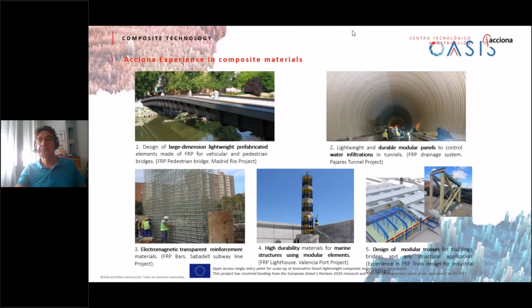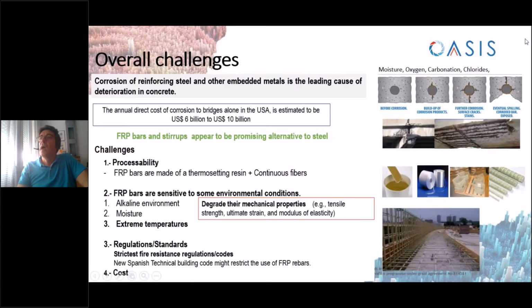So now, the question is, what are the challenges that Acciona proposed to OASIS? We are aware that in most civil engineering structures, corrosion is the main enemy and the leading cause of premature failure. The annual direct cost of corrosion in the US is estimated between 6 and 10 billion US dollars. In principle, a good concrete is supposed to provide adequate protection to the embedded steel. But over time, due to several chemical and physical processes, the pH value of the concrete decreases very slowly, initiating the corrosion process, which in turn causes cracks and spalling of concrete.